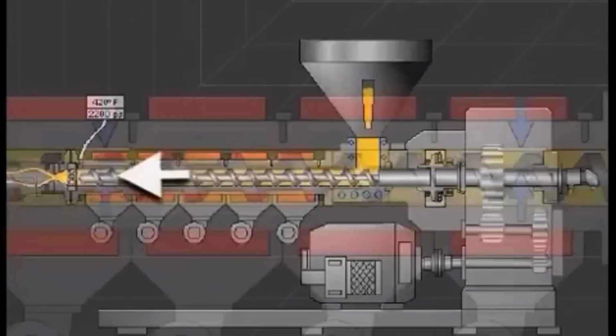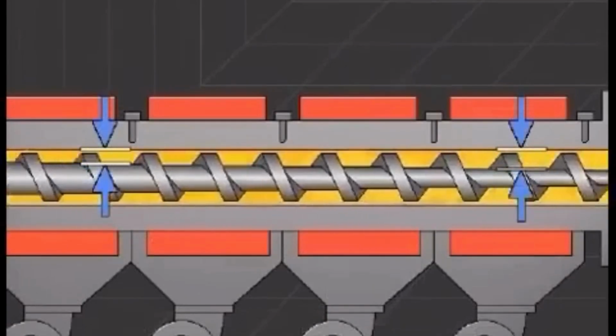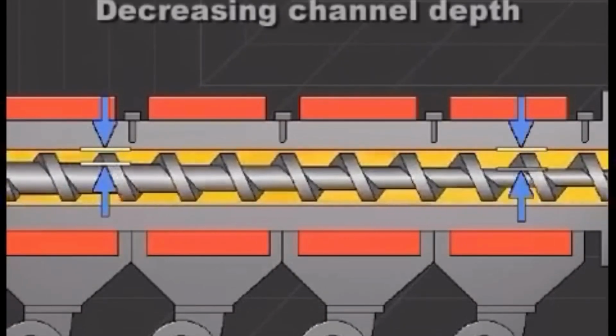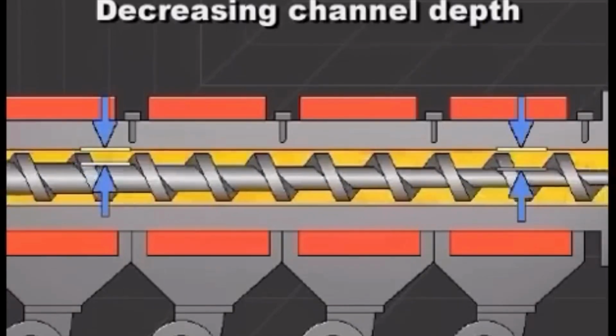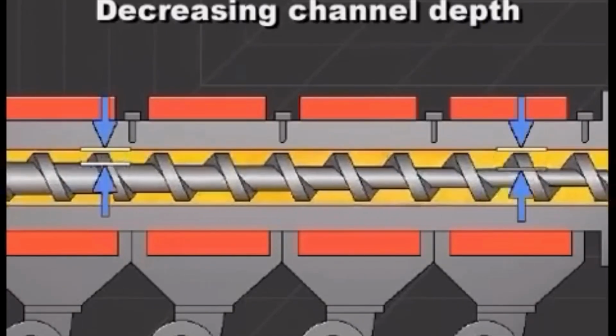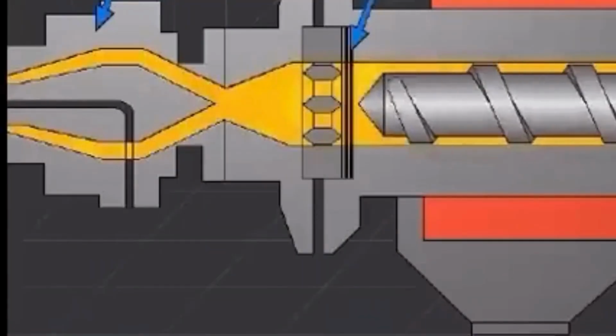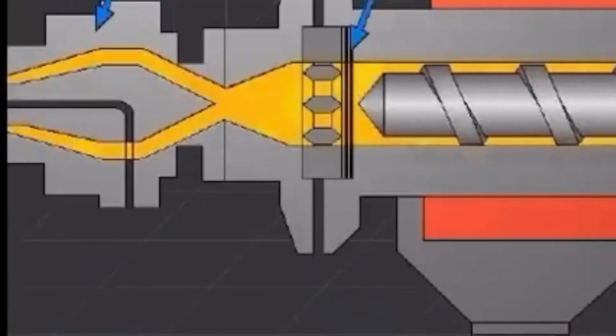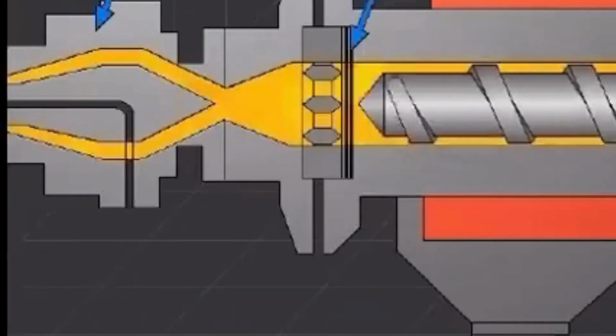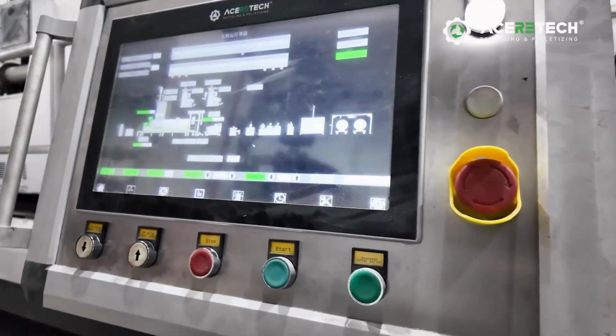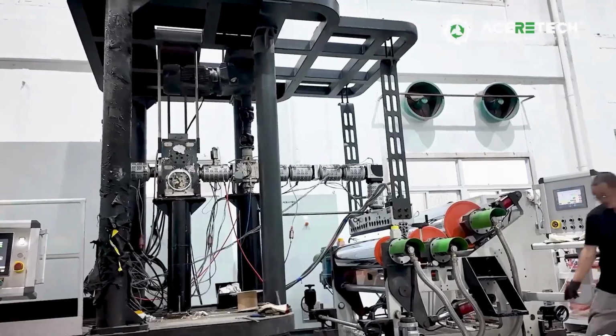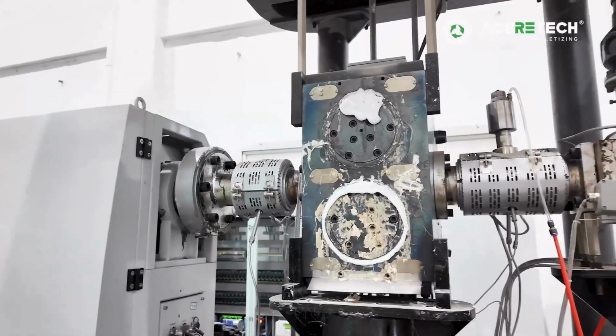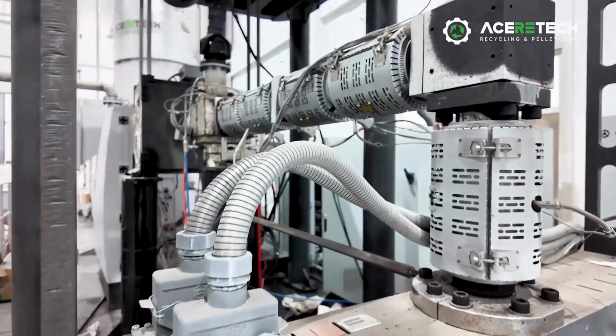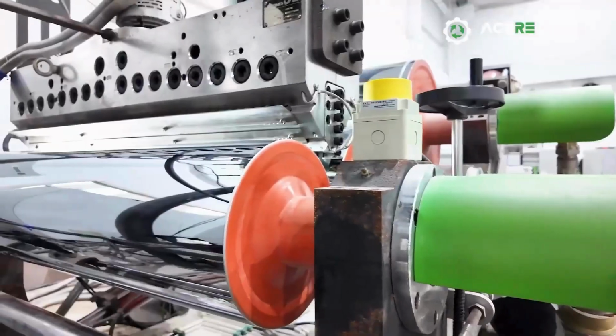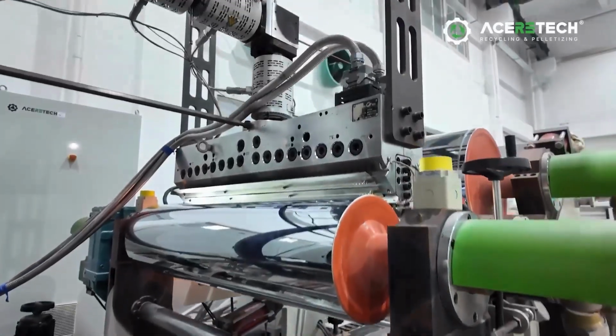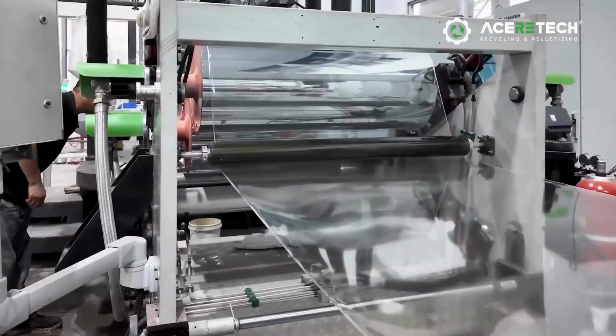After grinding, the regrind chips are blended with our selected ratio of virgin or post-consumer PET, depending on the production requirements. This blended material is metered into the extruder's feed throat, where the process of converting solid PET into new sheet begins. Inside the extruder, the chips are conveyed by the screw through a series of temperature-controlled zones. As they advance, the material experiences both heat and shear, gradually transitioning from solid particles into a fully molten, homogenized melt. Devolatilization ports help remove any remaining moisture or trapped gases, preventing degradation and ensuring optical and mechanical consistency in the final sheet.